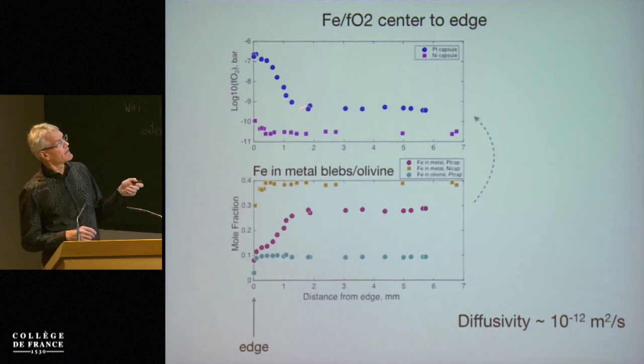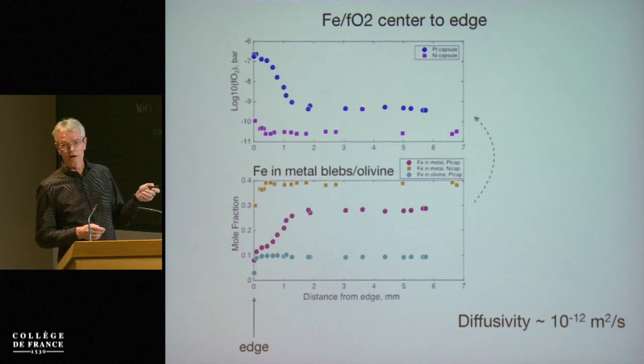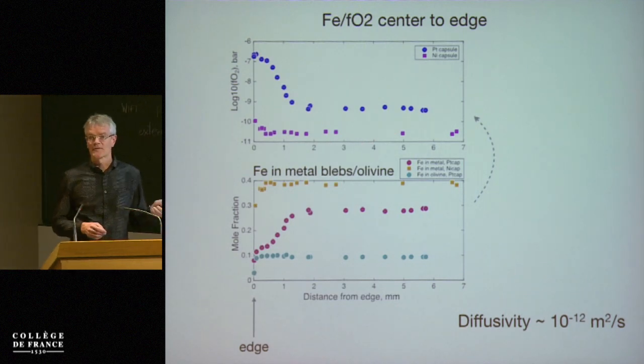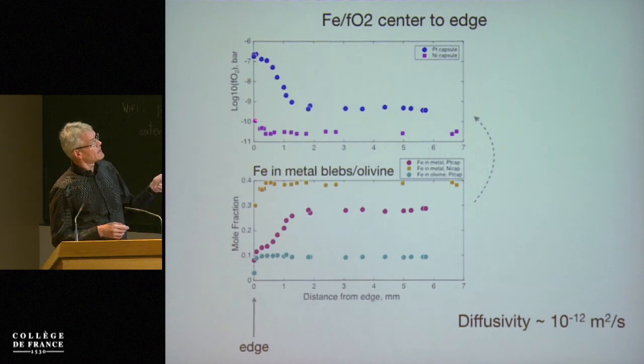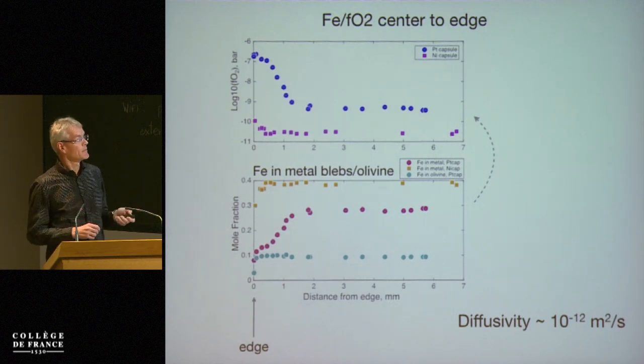Another important part is that in the interior, the oxygen fugacity seems to be constant. But if you compare a platinum capsule with a nickel capsule, the oxygen fugacity of the nickel capsule is lower, and the gradient in oxygen fugacity is much smaller in spatial extent than for the platinum capsule.